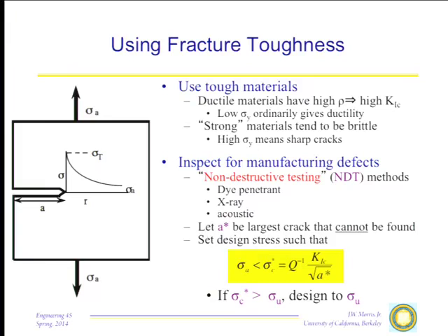Now test either half of the glass rod. I can absolutely guarantee you that either half of the glass rod will be tougher, have a higher breaking strength than the original glass rod did. Because the original glass rod broke where A was biggest. The two halves of the glass rod have smaller A's. Therefore, they're going to be tougher.